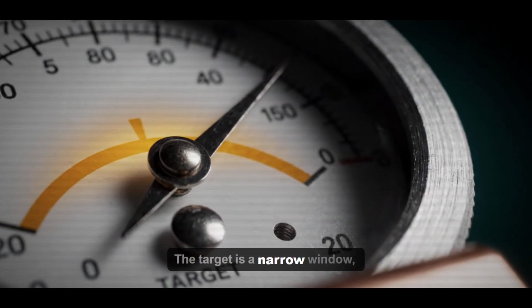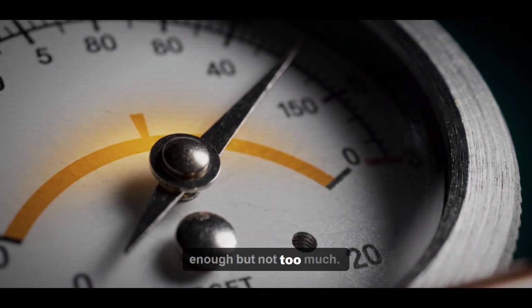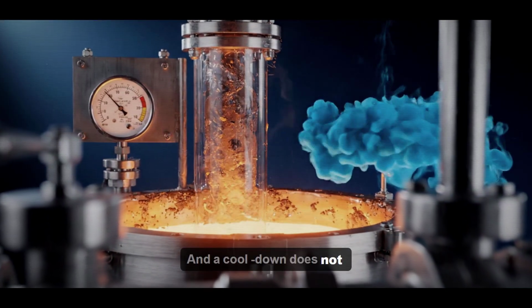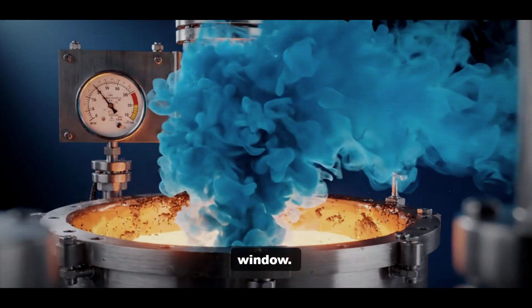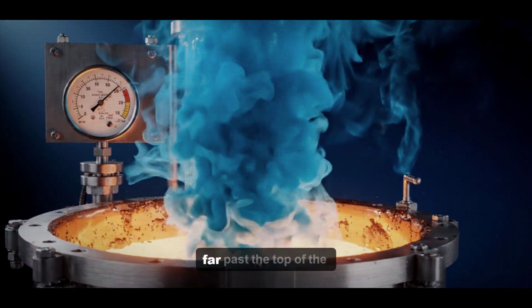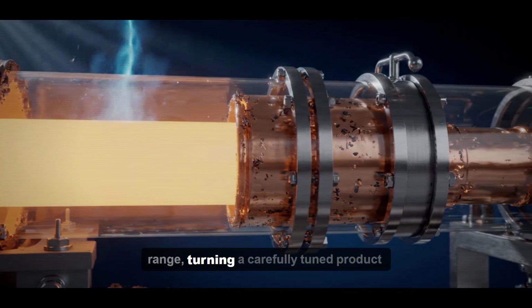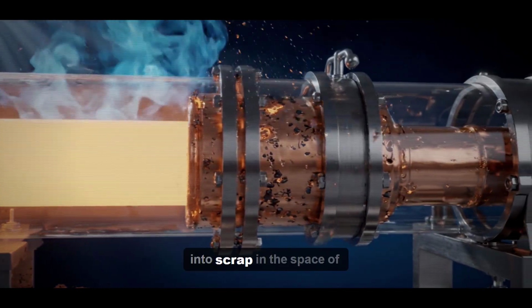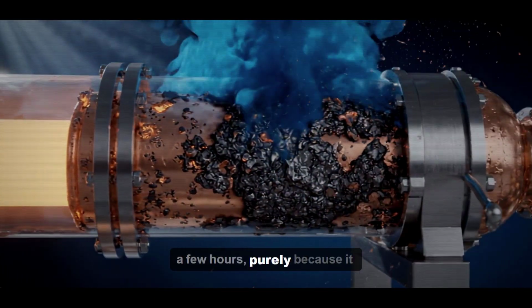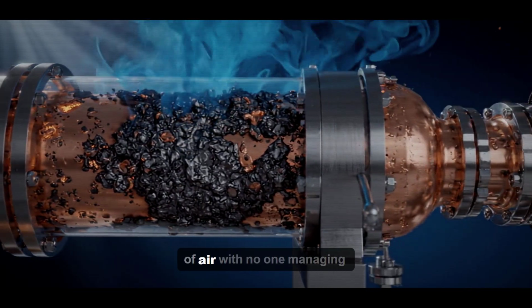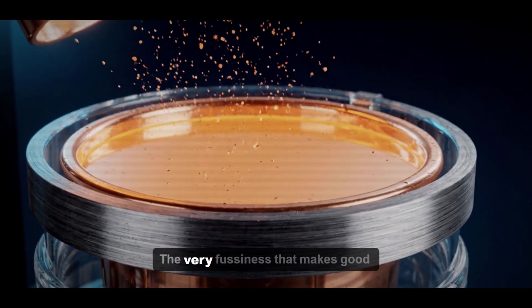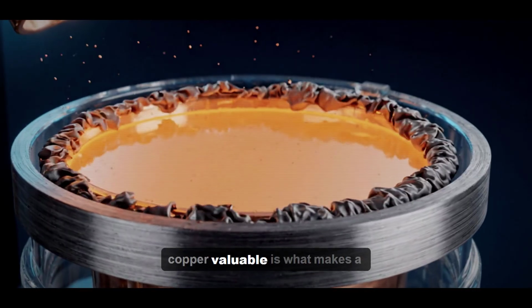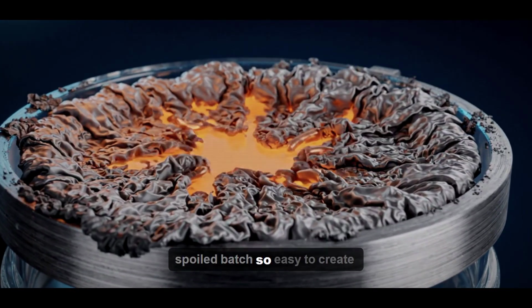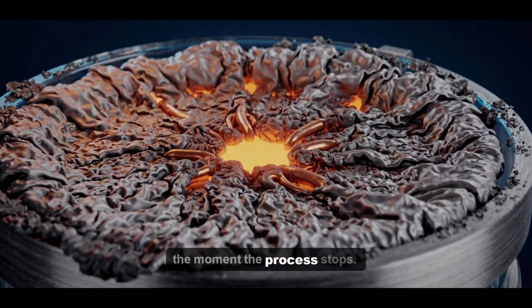The target is a narrow window, enough but not too much. And a cooldown does not gently nudge you out of that window. It floods the metal with oxygen far past the top of the range, turning a carefully tuned product into scrap in the space of a few hours, purely because it was left hot in the presence of air with no one managing it. The very fussiness that makes good copper valuable is what makes a spoiled batch so easy to create the moment the process stops.